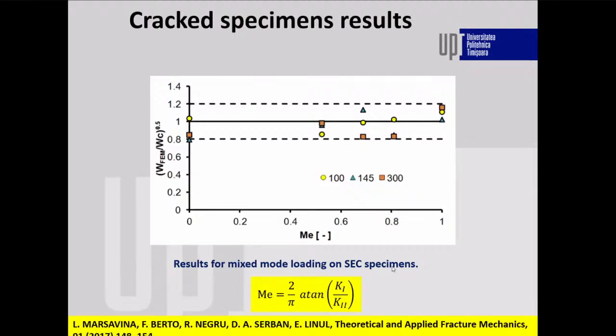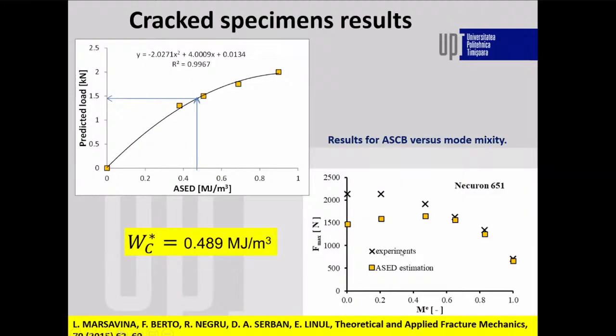We also tried to predict the maximum load. We kept the same control radius, and we found a polynomial equation between the predicted load and the average strain energy density, and for the typical critical strain energy density we predict the maximum load. These predictions work quite well for mode 1 and predominantly mode 1, but the predictions are lower by up to 25% for pure mode 2 and predominantly mode 2, these two points.